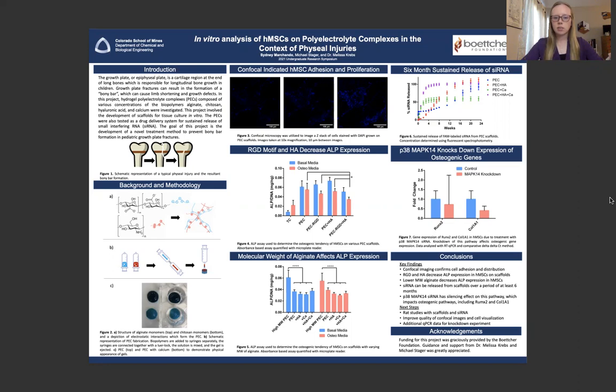PECs containing both HA and RGD, which is a peptide motif that enables cell binding, showed significant decreases in alkaline phosphatase, or ALP expression, when compared to PECs without these compounds. The molecular weight of alginate was also shown to significantly affect ALP expression, with a decrease for lower molecular weights.